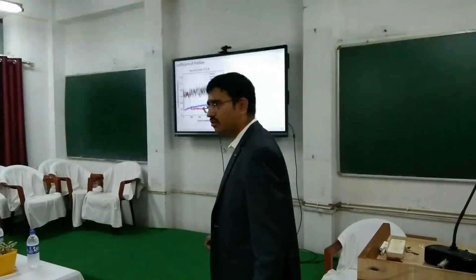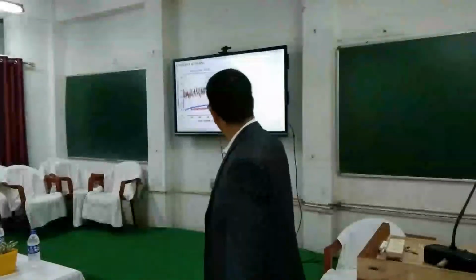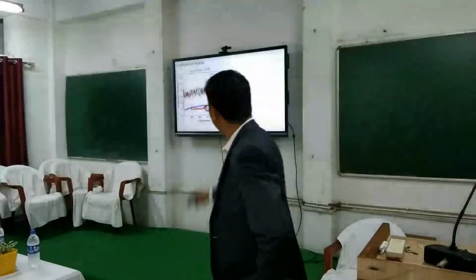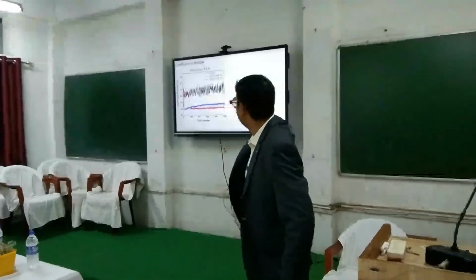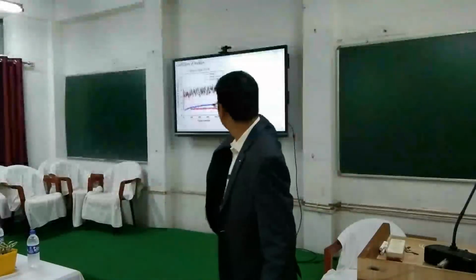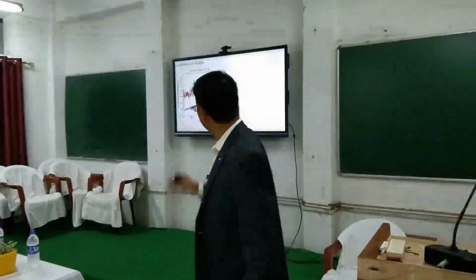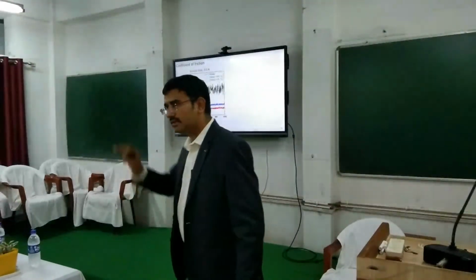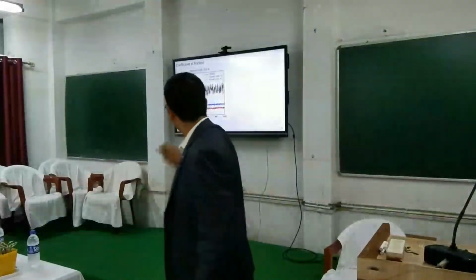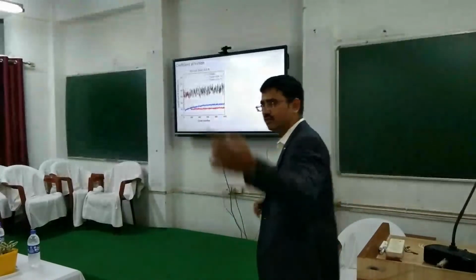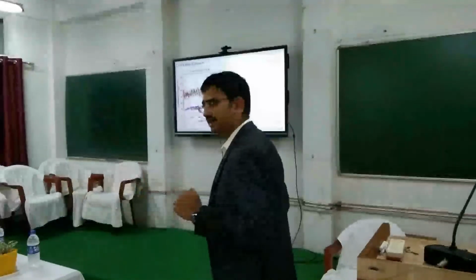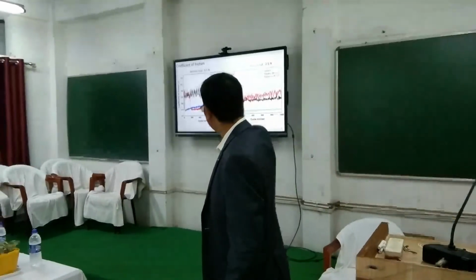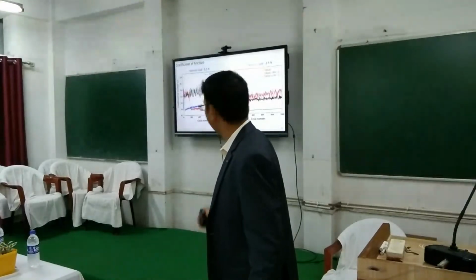So we looked first at the coefficient of friction, which was monitored during the entire test. You see that in the case of titanium 64, the friction is highly fluctuating, and the average friction is around 0.6. Whereas in the case of composite coating, that is with titanium carbide, initially it was the same, but after a few cycles it falls down and comes to an average of 0.3 or 0.33 depending upon the titanium carbide. So you see that reinforcement of carbide particles had actually decreased the friction. That is one observation. Even at higher loads, when we changed the load, we could see that there is a drop in friction in the case of composite coatings with higher titanium carbide composition. We will see why this happens.